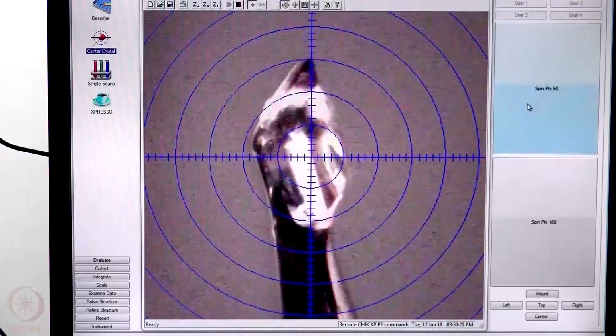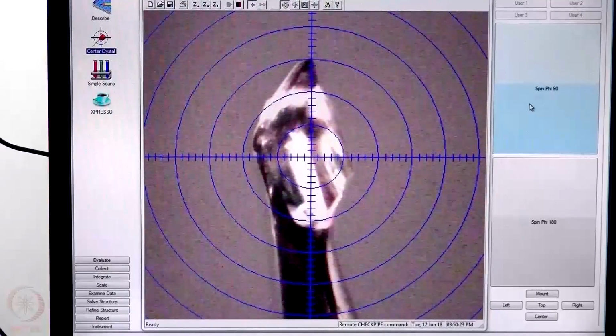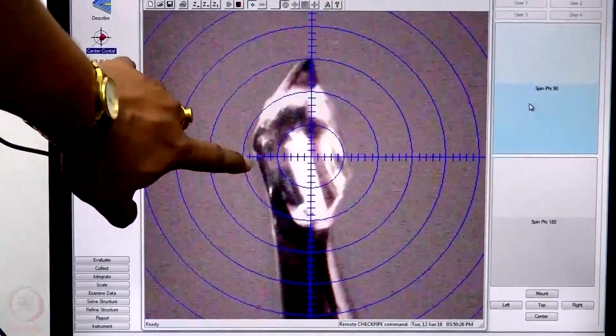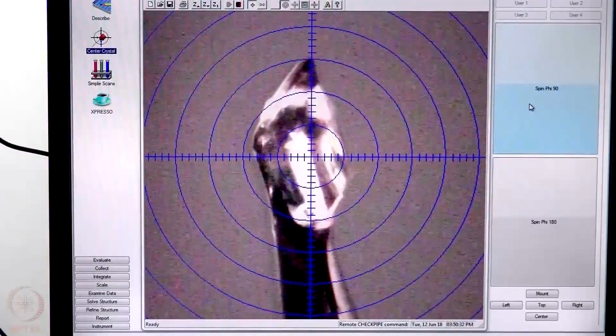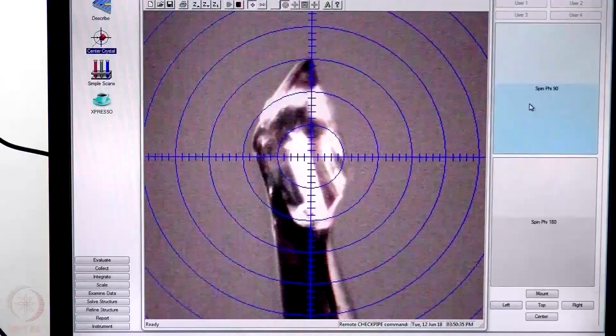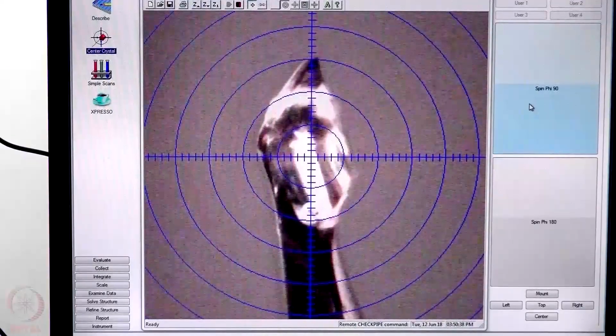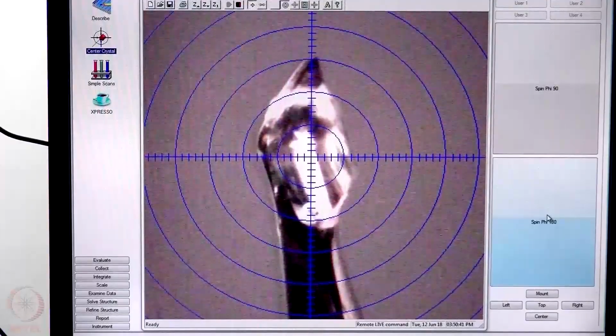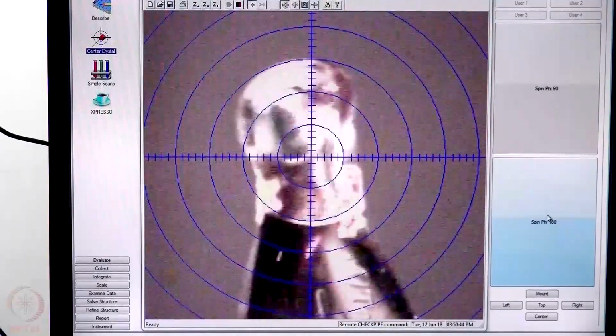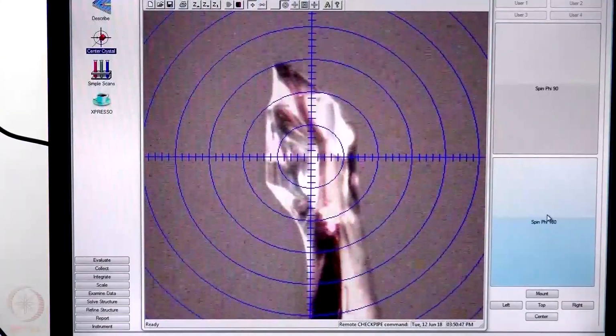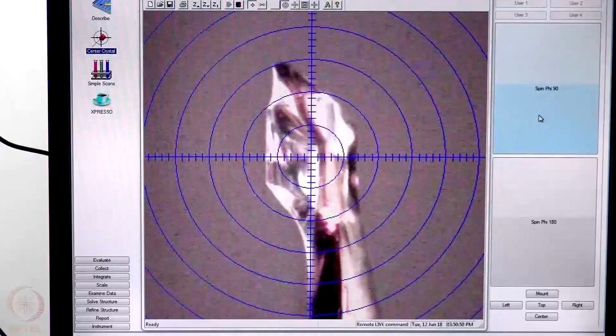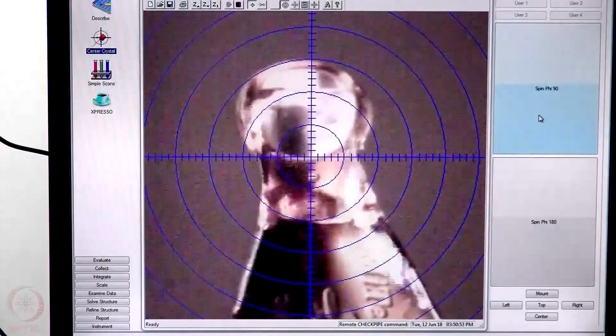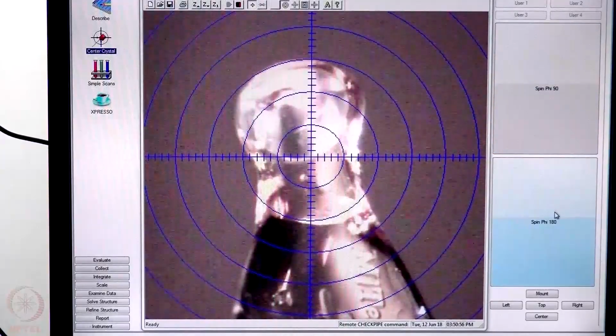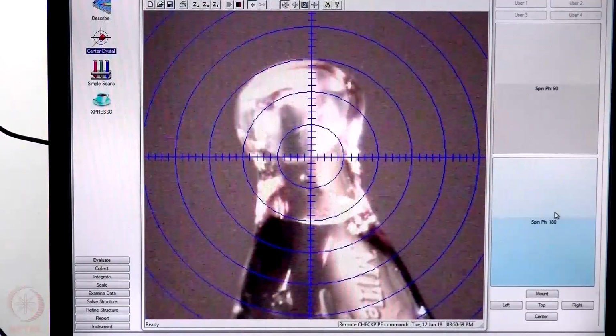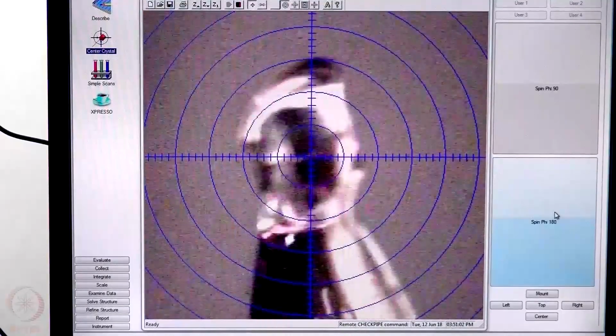We need to check all the 90 degree rotation positions for centering the crystal. Here what we see is it is slightly more towards the left compared to the right. So we slightly move it to the right and rotate it by 180 degree to confirm. Fine. This is also okay, and then we change it to 180 degree, it goes there.